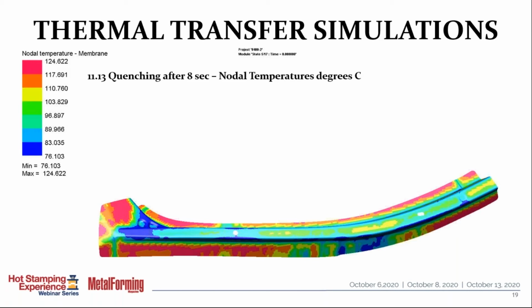The last thing we really check is how, after we get the tool to bottom and it's properly formed, no splits or wrinkles, and we didn't get too cold before we finish forming, what is the quench rate? So we have a requirement to get below at least 200 C, optimally 170 C on material before we remove it from the die. Some parts are more sensitive to that than others, but once you're below that 200 C, you should be fully martensitic.